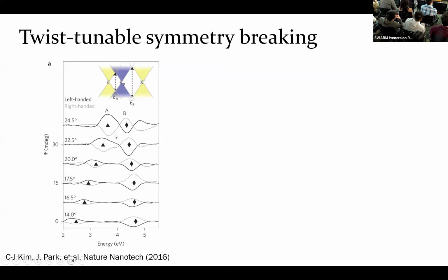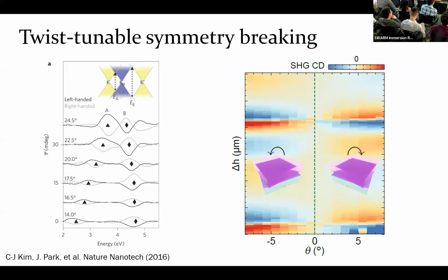Okay. But now you see that this measurement was done with many samples. Each curve is basically a different sample, because you have to make a different sample to get a different twist angle for twisted bilayer graphene. But now we don't have to do this. Now we have this new mega 2D technology, and we can measure the circular dichroism of this symmetry breaking in just one device. And the result is shown here.